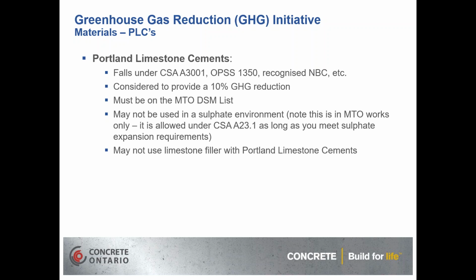If we're using limestone cements in MTO works, the cement must be on the DSM list, the Designated Source Materials list, where we can find that on the roadauthority.com website. It may not be used in MTO works in a sulfate environment. And this is something specific to MTO only at the moment. It is allowed under CSA A23.1. There was recently an amendment a couple of months ago published that just aligned that with the cement standard, and basically it's treating the limestone cements exactly the same as a regular Portland cement, where it has to meet the sulfate expansion requirements. And the other consideration with the Portland limestone cements for the MTO works is that we may not use a limestone filler with the Portland limestone cements. So it's only one or the other in this case.